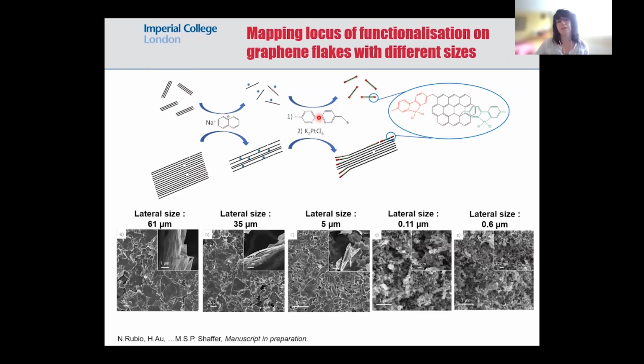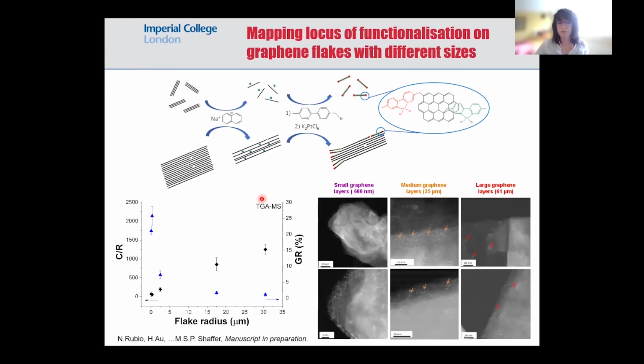We charge them with sodium naphthalide, and then we were able to functionalize with this bipyridine molecule that can complex platinum atoms. So in this way, we are introducing a molecule that can complex these platinum atoms, and we will be able to see these platinum atoms in scanning transmission microscopy. So in this graph, we were able to see how the grafting ratio changes according to the flake radius. If we look at the blue trend, for smaller flakes in the range of hundreds of nanometers, we obtain moderately high grafting ratios, and these ratios decrease as we move on to higher flake radius.